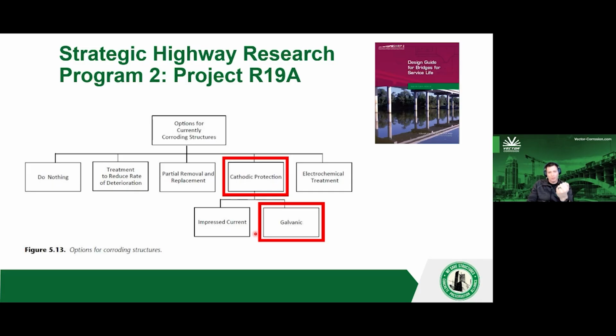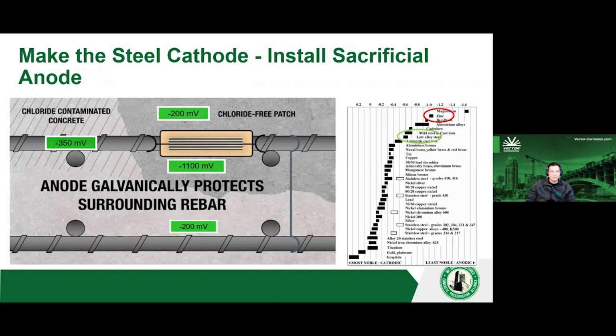But I am going to discuss cathodic protection, and specifically galvanic. So cathodic protection, I defined it up front. That's trying to make the steel the cathode part of the corrosion reaction, the non-corroding electrode, by making something else the anode. And galvanic, that basically means it's natural. We're using a dissimilar metal that's going to have a natural electrochemical difference that will cause this galvanic corrosion cell. And what does that look like? And it looks like this. Zinc, you can see this is a galvanic series of elements on the right.